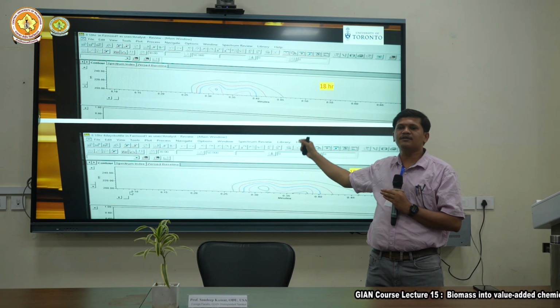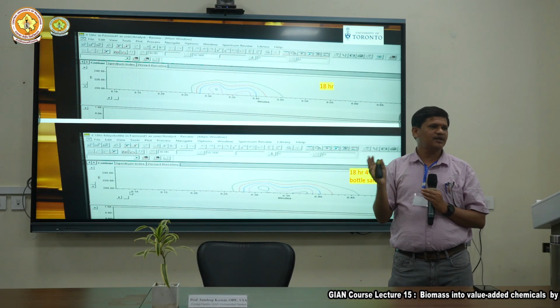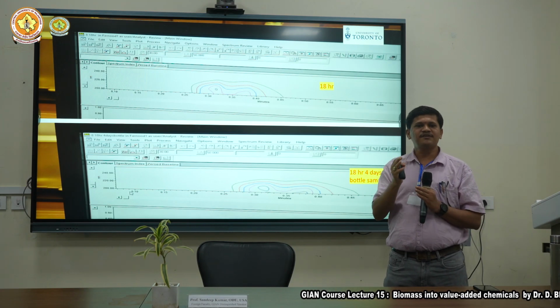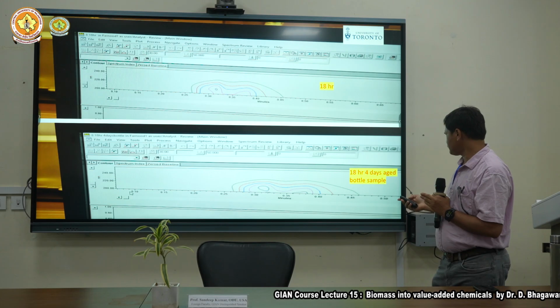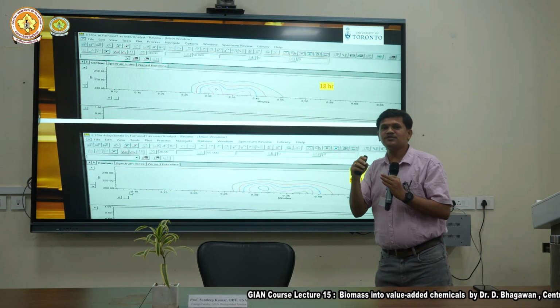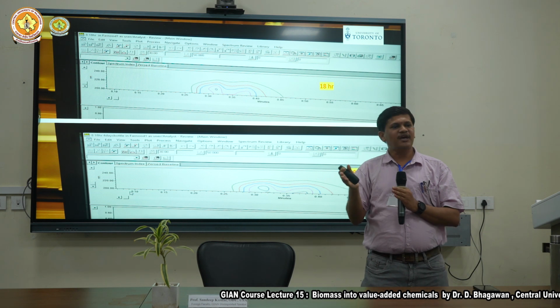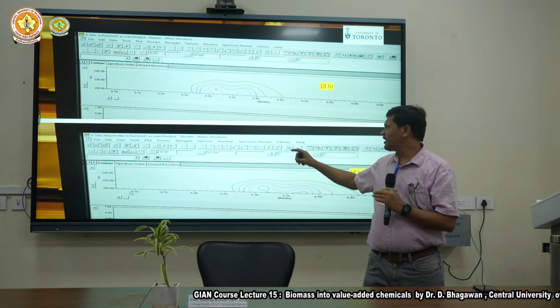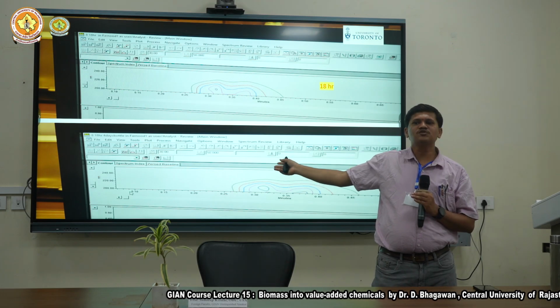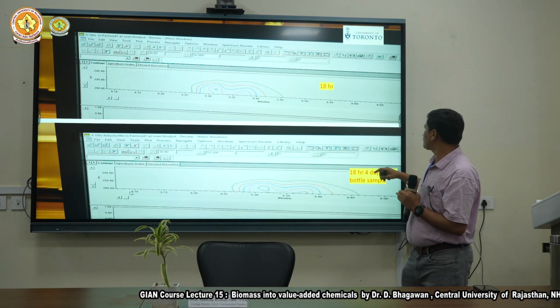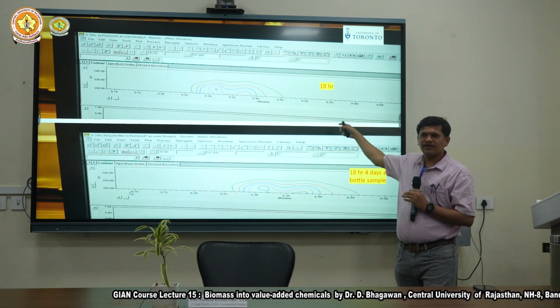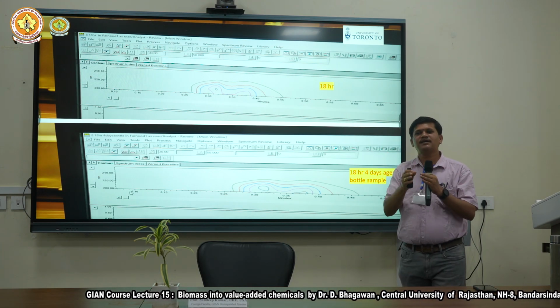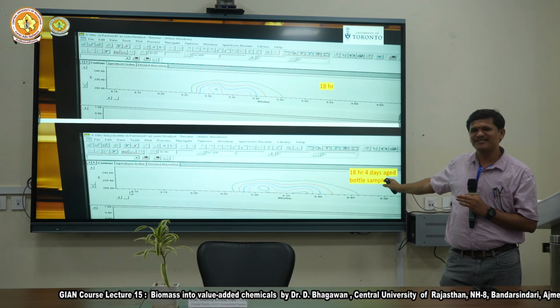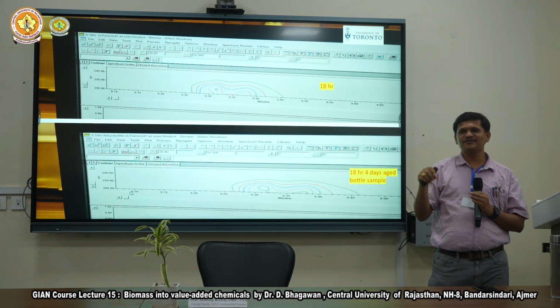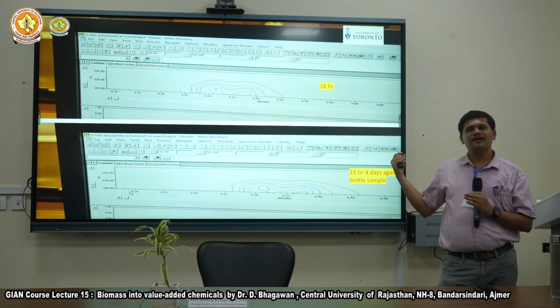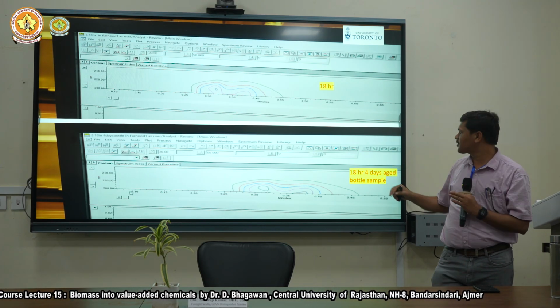Whichever catalyst we develop, it has the capability to cut at selective sites, meaning the energy it gives is specifically cutting the lignin compound. Some chemical reactions may have forward and backward reactions, but here it is only a one-way reaction. There is no backward reaction. As proof, we continued the reaction up to 18 hours, and after that I retained that sample for 4 days. This was an unintentional experiment. I think during holidays I kept those samples in the lab, and after that I repeated the analysis and found, you can see the comparison.